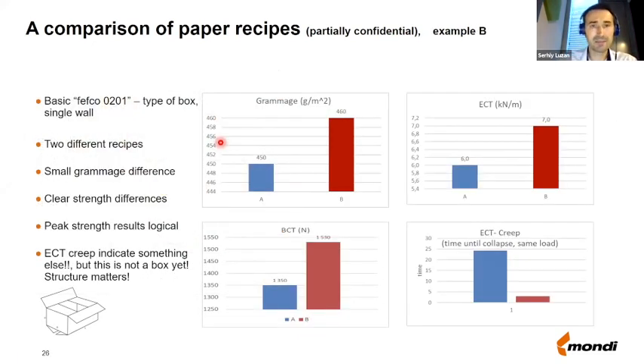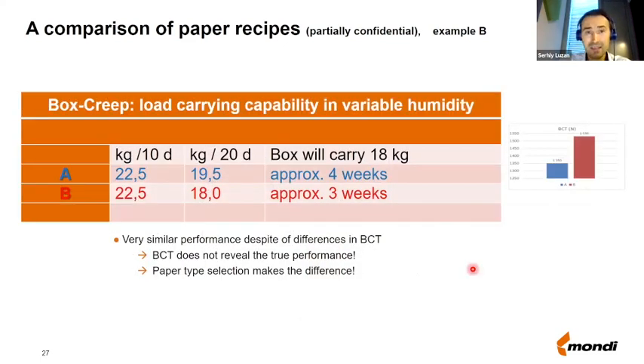And here is another example. Again, we tested two different types of corrugated boards and two different types of boxes, which had quite a similar grammage, 450 or 460 GSM. Interestingly, the recipe A had lower ECT values and also quite lower BCT values. But then when we tested the creep performance on the corrugated board sample, then actually this creep performance was the opposite. So you see that for a regular ECT test, the A recipe had lower ECT values, but for the creep test, keeping the corrugated board under constant load, actually the A recipe was even stronger. And the same tendency we saw also when we tested the boxes at this constant load conditions.